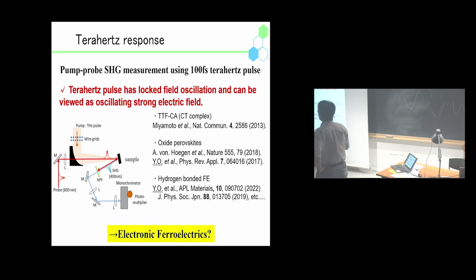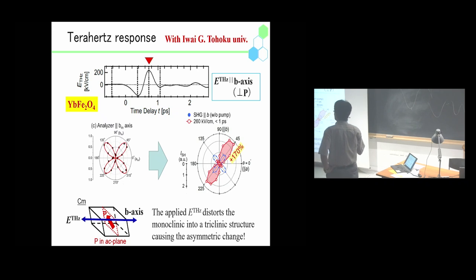Here is the experimental setup for the pump and probe SHG measurement using the 100 femtosecond terahertz pulse. We irradiate the pump pulse, namely the terahertz pulse, using a parabolic mirror onto the samples. Then we irradiate the 800 nanometer pulse through the parabolic mirror onto the samples, and we detect the generated SHG using a filter, monochromator, and photomultipliers. Then, how about the electronic ferroelectrics in the pump and probe SHG measurement? For the pump and probe terahertz spectroscopy measurements, I collaborated with the Iwai group at Tohoku University. This panel shows the applied electric field waveform. The maximum value of the terahertz field is about 200 kilovolt per centimeter. We apply the electric field along the b-axis, perpendicular to the polarization.